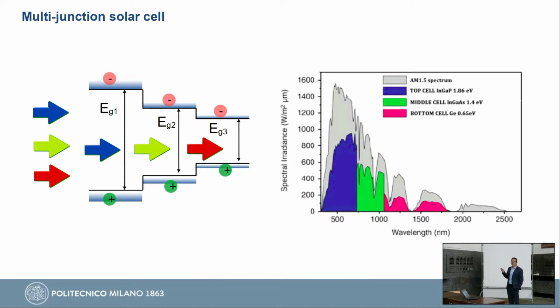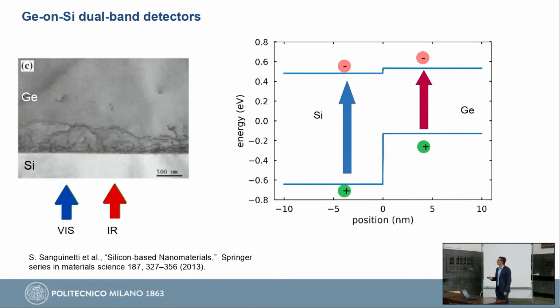So, inspired by this approach of using different materials for absorbing different parts of the light spectrum, we thought to use this idea not to make a solar cell, but to make a photodetector. We are not interested in generating power, but in reading a light signal. So what we did, we put pure germanium on top of silicon. Now you should know these are the defects required to relax the germanium. And we have seen that these two materials have very different absorption properties. So if I shine a mixture of visible and infrared light, the visible light will be absorbed in the silicon, and the infrared light will be absorbed in the germanium.